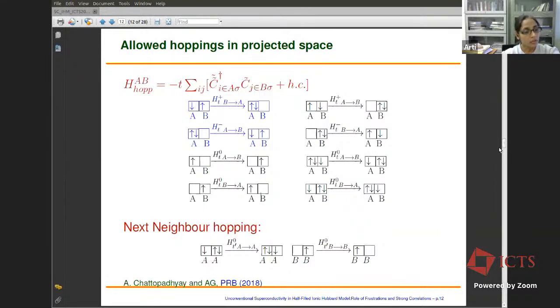And if you have the next neighbor hopping, which will play a very crucial role in stabilizing the superconductivity, as I will show you after a few slides, then again we can have a hopping of doublons within the A sublattice through the second neighbor hopping, and we have a hopping of holes within the B sublattice. So even at half filling in this strongly correlated model, there is enough charge dynamics in the system, and both the first order and the second neighbor hopping processes are allowed, although not all the hopping processes are allowed.